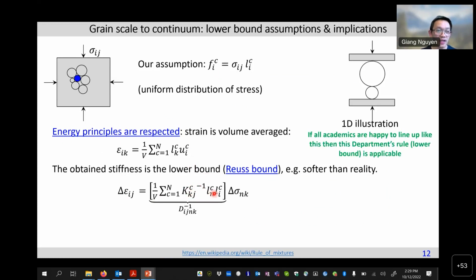But the underlying physics here is that to do that, we have assumed something. And that assumption, if we put it in a 1D case, would look like this. The grains should all be lining up that way to make our assumption valid. It's equivalent to a system of springs in series. When we do that kind of homogenization, we get the stiffness of the system that is smaller than the real stiffness. So in other words, we have implied some rule here, and that rule leads to something different from reality.